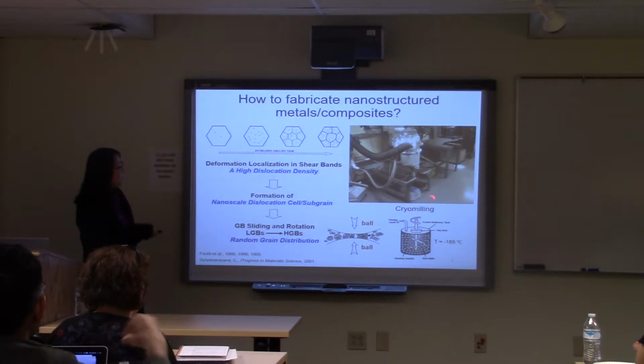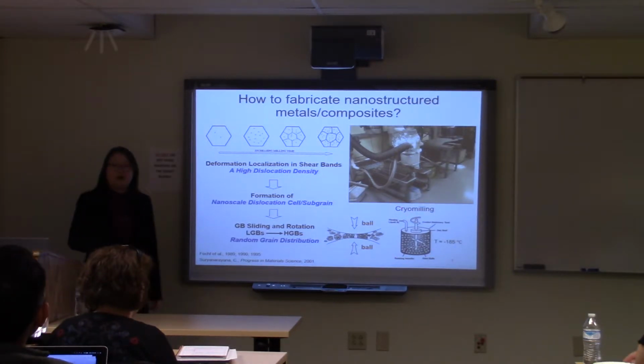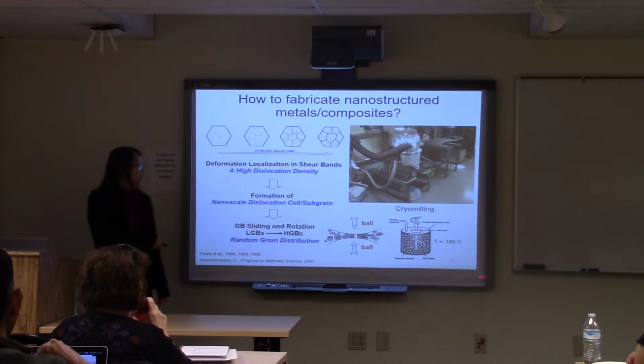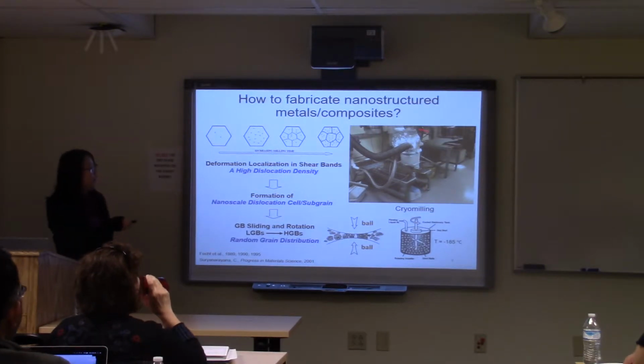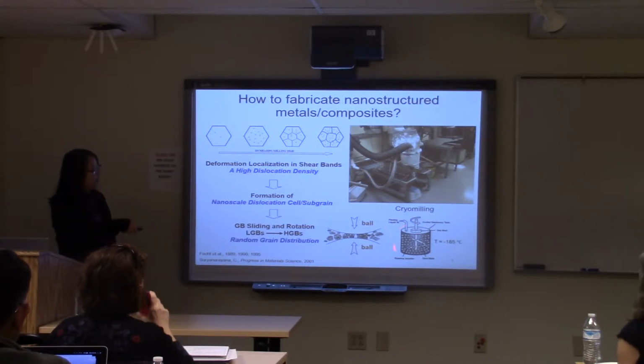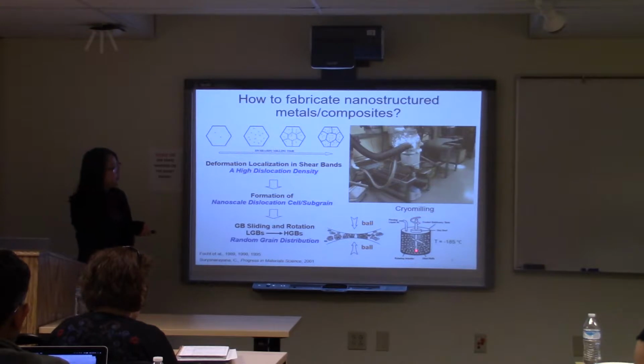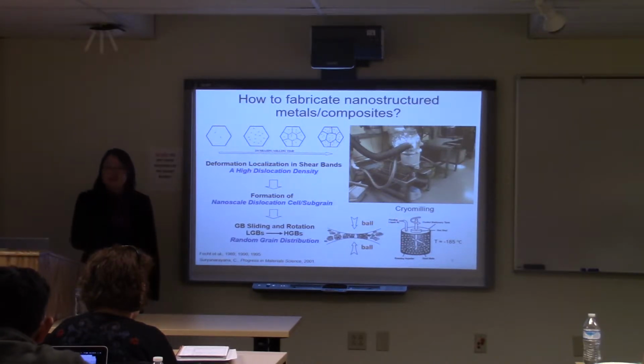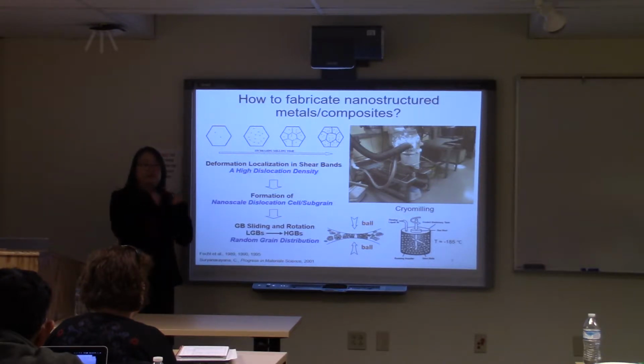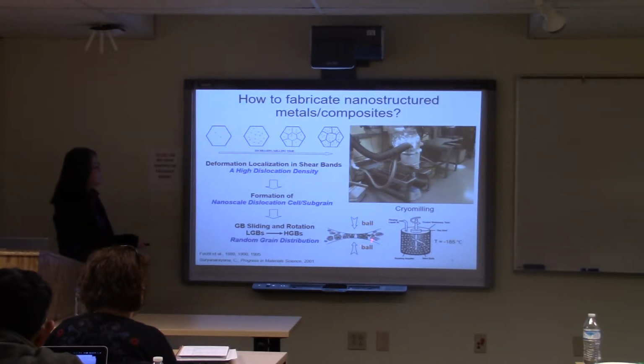The technique I have been using is called cryogenic ball milling. This schematic shows one apparatus, a real apparatus. During the milling, the powder is milled inside a slurry made of milling balls and a liquid cryogenic medium, for example liquid nitrogen. The impeller rotates at a very high speed, and we take advantage of the collisions between the balls, the impact, to deform the particles.